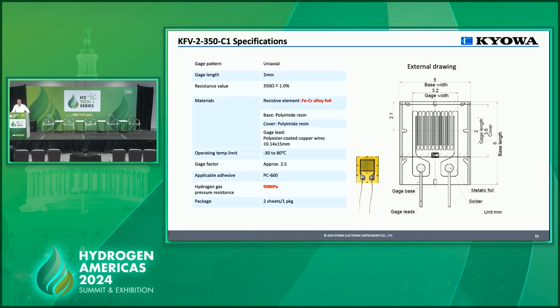This is the main specification of KFV strain gauges. The specialized point is the material in the sensing portion. We use iron chromium alloy foil in the resistance element, the sensing element. This type of foil is more stable in resistance against hydrogen embrittlement. So this strain gauge is not affected by hydrogen embrittlement during the measurement process. Also, our past research project revealed that this strain gauge was durable and applicable for a high pressure range up to 90 megapascal hydrogen gas exposure.